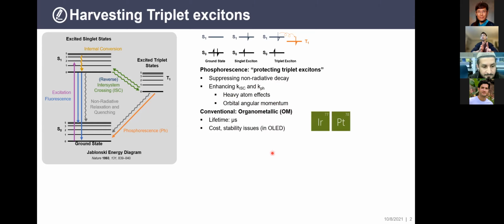Conventionally, when people design phosphorescence materials, they use organometallic complexes involving heavy metals. This is what I'm talking about, the heavy element effect. Because we're using metal, the atomic size is really, really big, so they can have a very great heavy element effect, which causes the lifetime of these triplet materials to be very short. The triplet exciton is not that long-lived. They can fall into the regime of microseconds, but they do have a lot of issues like cost and stability, especially when you're talking about higher energy excitons.